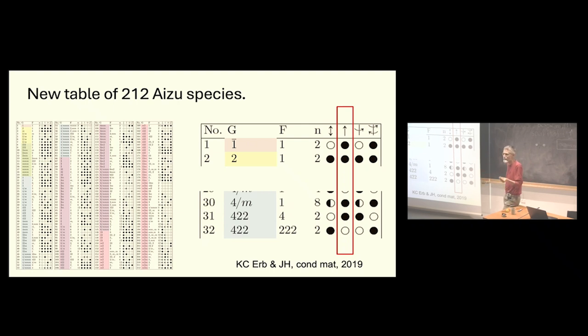But to switch it, in old times, basically means that there are domains. Now we can switch everything because we are so powerful. But in old times, it meant there was a domain wall which you can pass through. And if these domain walls differ by some component of something which transforms as polarization, then it's ferroelectric.